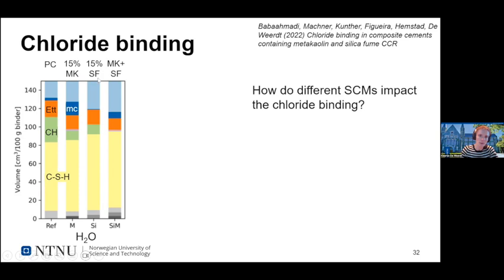If we use 15% silica fume, we also have a reduction in the green Portlandite content. We get more CSH, but we don't get an increase in our AFM phase, as we're not adding more aluminates to the system. And if we combine 15% metakaolin with 15% silica fume, we actually consumed all Portlandite, so there was no Portlandite left, and we form a lot more CSH and some more AFM. So we had these hydrate assemblages to start with.